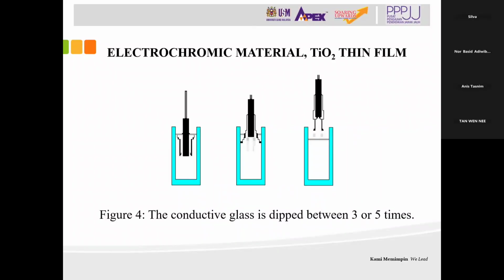The titanium dioxide thin film was prepared from tetraisopropyl orthotitanate solution and ethanol as a solvent by the sol gel dip coating technique. All of this is done on the ITO glass substrate. The film was deposited after a calcination process at 500 degrees C for 1 hour. This figure shows how the TiO2 thin film is deposited on the conductive glass. The conductive glass is dipped 3 or 5 times. After the first dipping, it is transferred for drying in the oven for 1 hour. Then we proceed with further dipping and repeat similar steps 3 or 5 times.